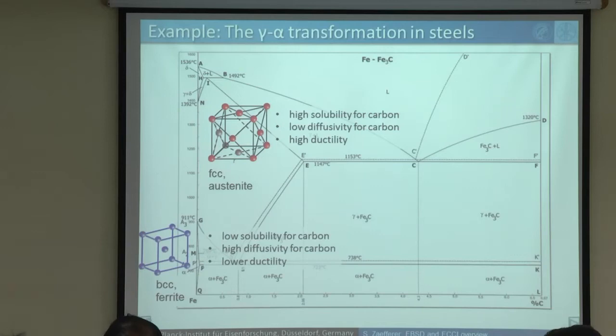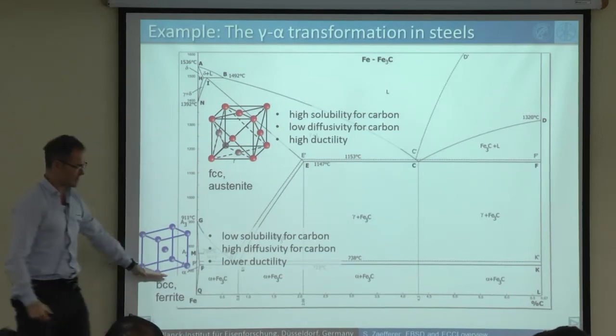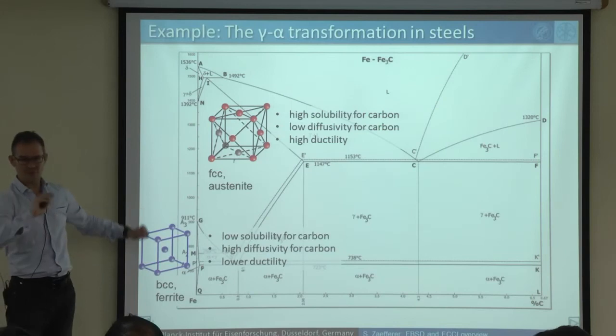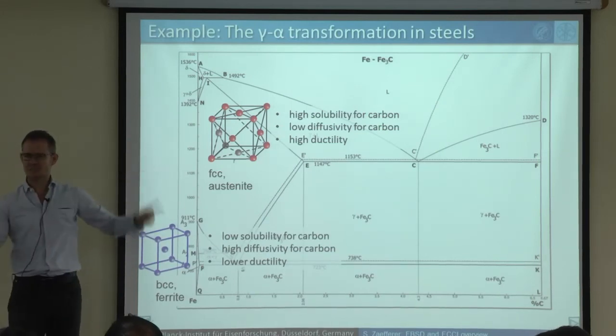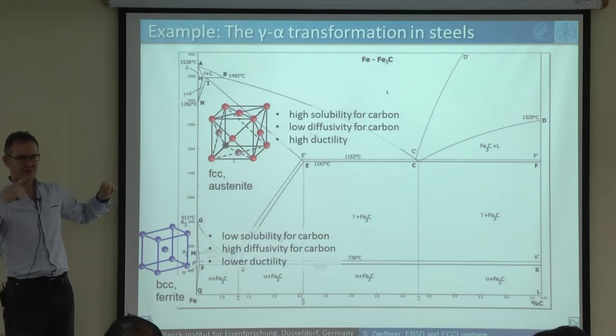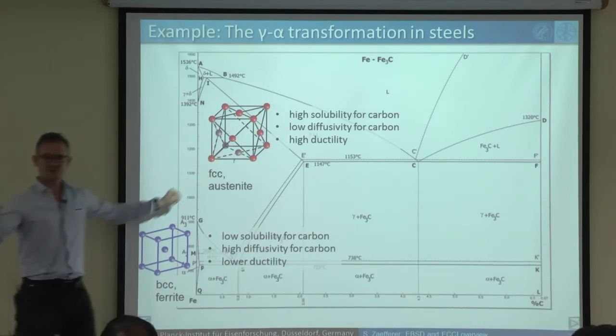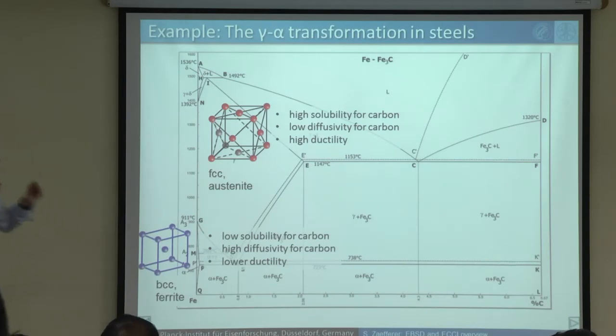Yeah? And by heating a material up to austenite and then cooling it down in a particular way, I will have more examples later, you can create all kinds of complicated structures. And you can create all kinds of complicated phase transformations. You have a diffusive phase transformation, which leads to just standard ferrite, but you have a bainitic transformation, and you have a martensitic transformation, so a displacive transformation. All this depends on these different properties of these two phases. And the interplay between these phases creates an incredible amount of things which you would like to understand.